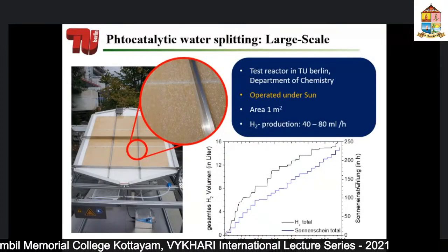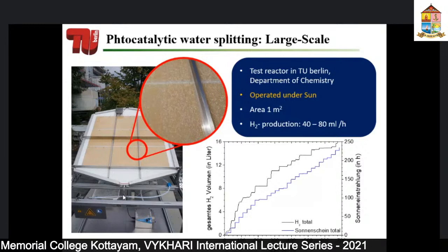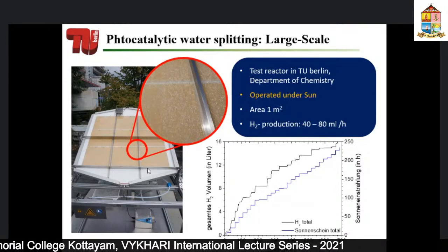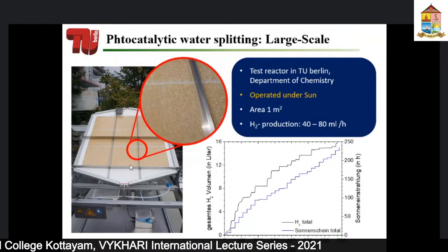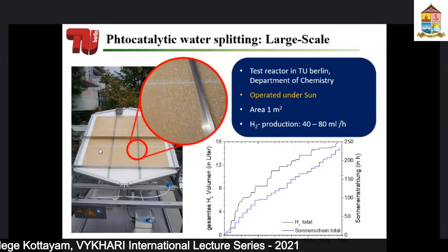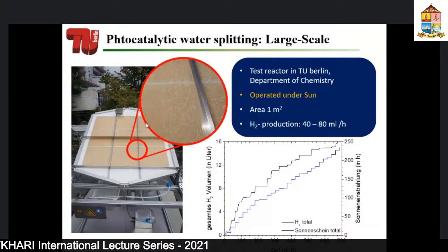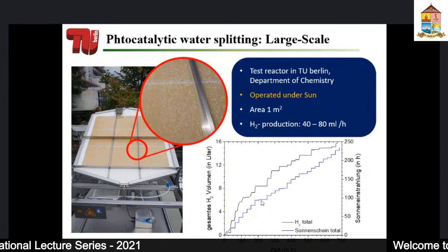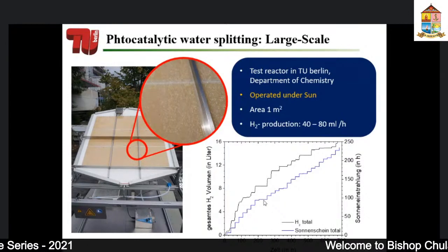We also show that we could make hydrogen on a very large scale. So these are the plates on which we deposit our carbon nitride, and this is on the rooftop of our chemistry building, and we put it to real sunlight conditions. The area is almost 1 meter square, and we could produce a large amount of hydrogen, which is almost 80 ml per hour. This is also, you can see from the graph, but you also see some amount of decrease because in the night we don't have sunlight, so you also have a decrease in your hydrogen production.